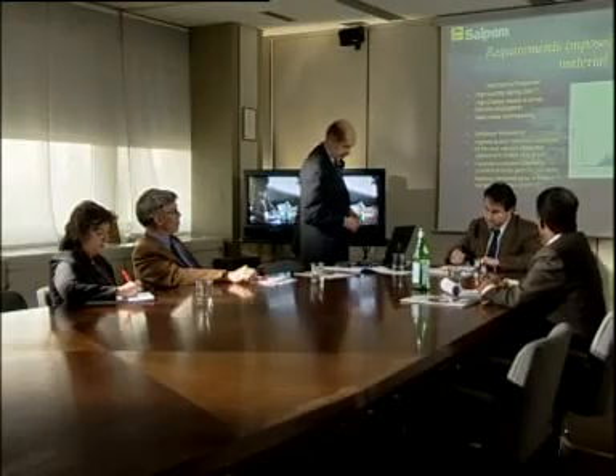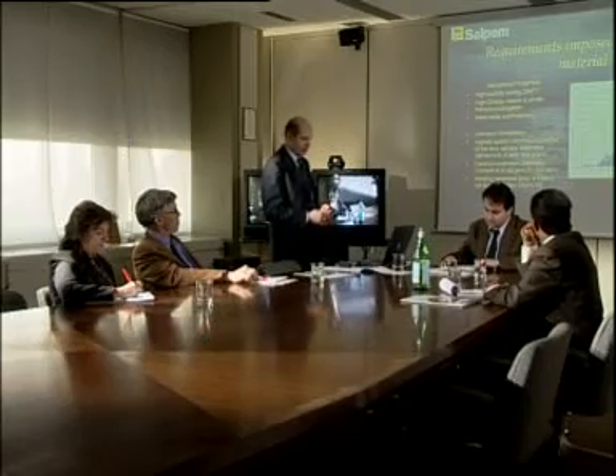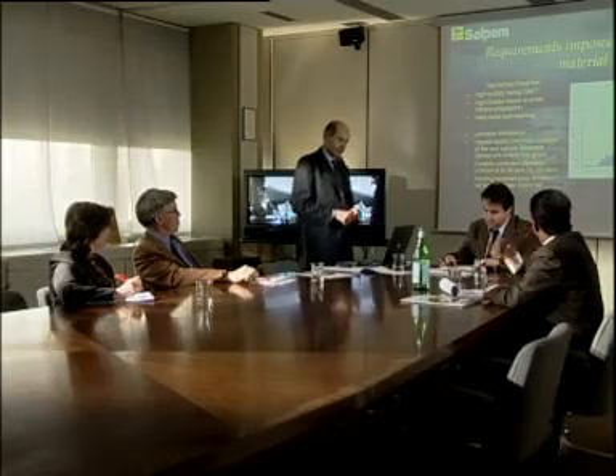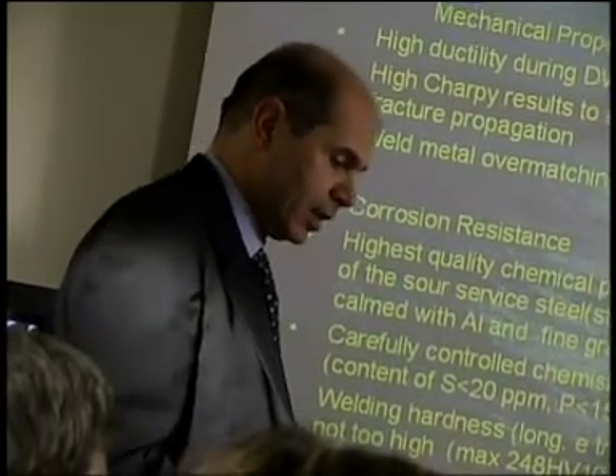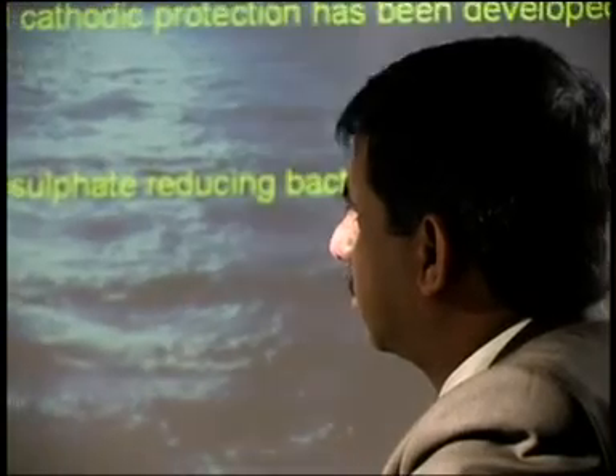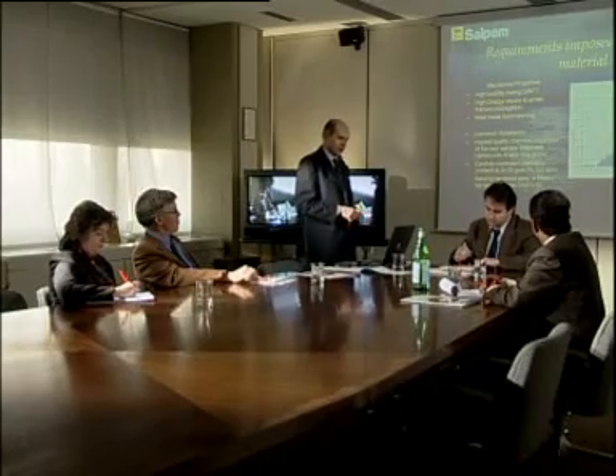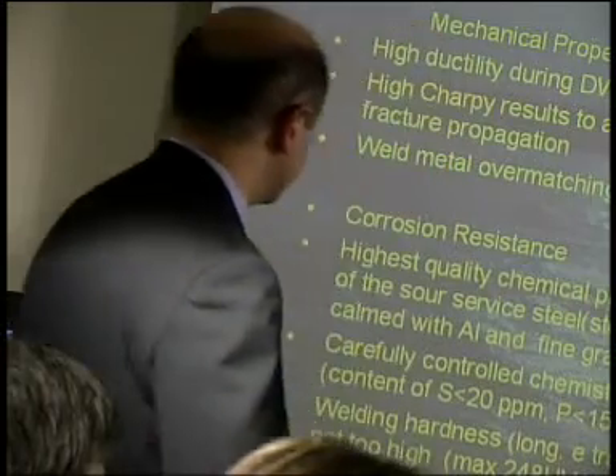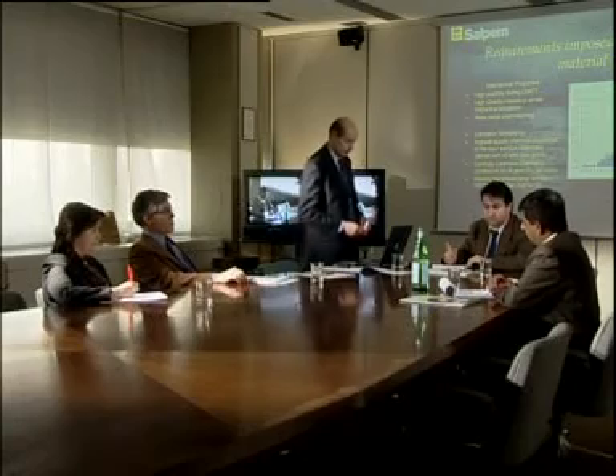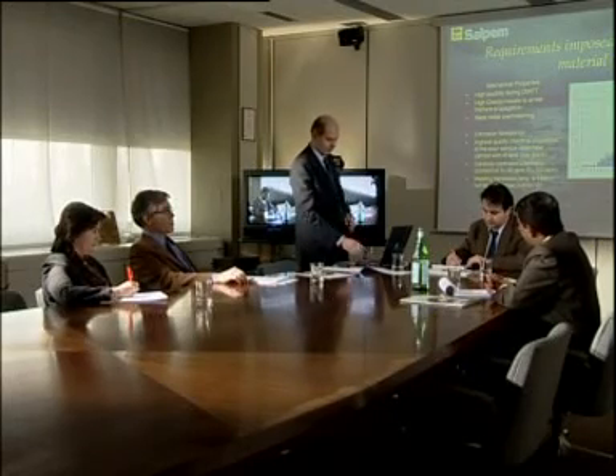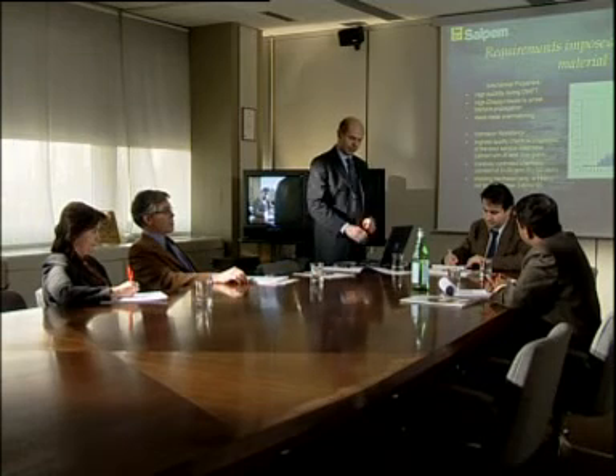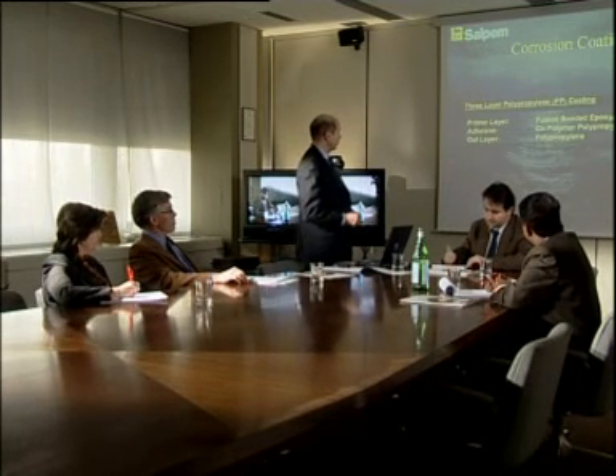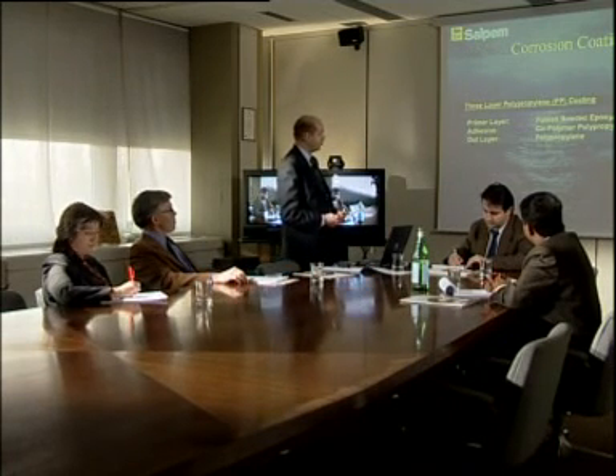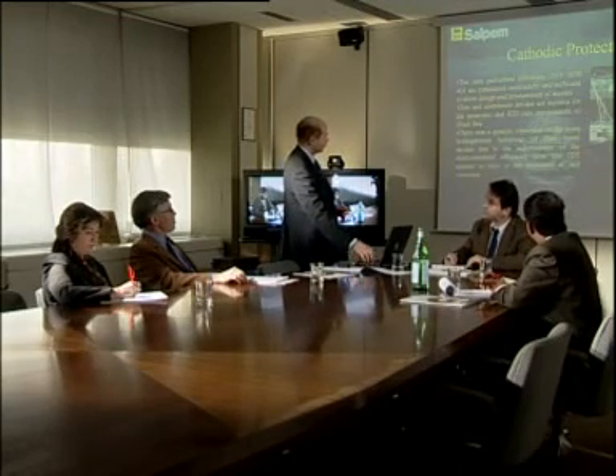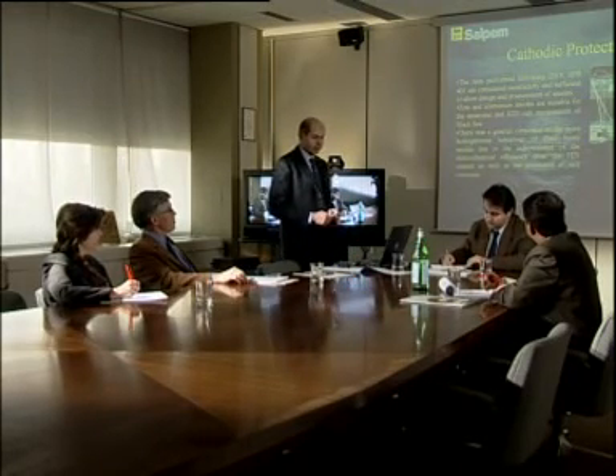The design of the pipelines had to take into consideration H2S concentration in water depths greater than 200 meters. The pipeline characteristics have been strictly defined within selected ranges of mechanical properties and corrosion resistance. For this type of Black Sea environment, what type of corrosion coating and cathodic protection has been selected? A 4mm 3-layer polypropylene coating has been selected, and for the anodes, zinc anodes have been preferred.